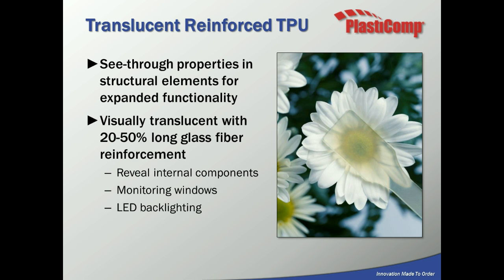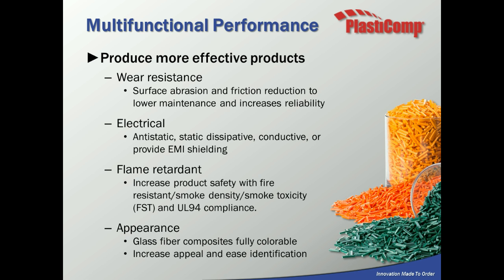One other unique product that I'd like to highlight is our thermoplastic polyurethane, and this is a translucent grade, where we can load the material with 20 to 50% glass reinforcement, get a structural type material, but also have it translucent. So we can have it in components where you want to reveal internal components, such as housings, monitoring windows for fluid levels, and in some applications, LED backlighting. Again, we can incorporate multifunctional performance through the addition of additives like flame retardant agents and lubricants for wear resistance on top of our long fiber thermoplastic materials.